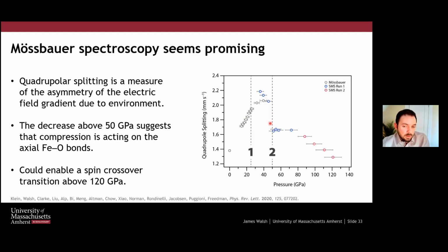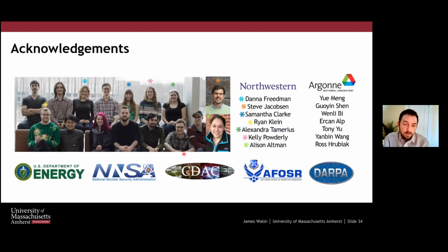After the second phase transition, we now seem to be decreasing the quadrupole splitting and actually getting to lower values than where we started. So the suggestion might be that above 120 GPa, we're actually compressing all those bonds at the same time. And so we might actually see a spin crossover if we just keep going. But of course, we've both moved on from this project, and we'll see if anybody else picks that up and sees if that's true. Okay, and so with that, I'll stop talking.